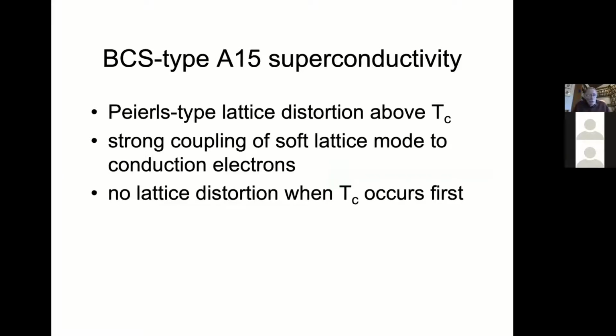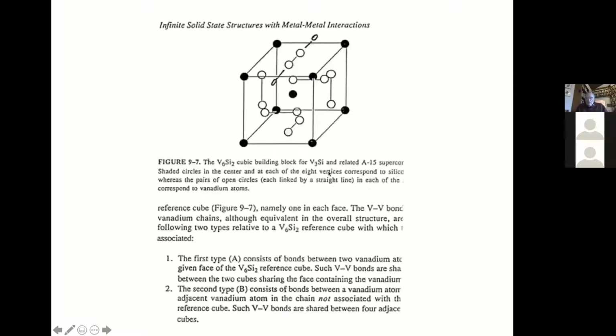So let me turn back to what was considered a high TC material when I was a graduate student: the so-called A15 superconductors, niobium-3 tin and V3Si, for example, and eventually niobium-3 germanium and extrapolated niobium-3 silicon. It turns out that in these materials there's a Peierls type, it's not actually a Peierls type distortion, but I'll describe it. There's a lattice distortion from cubic to tetragonal above TC, and there's strong coupling of this soft lattice mode to conduction electrons. And I'll discuss what happens when TC and this transition temperature cross.